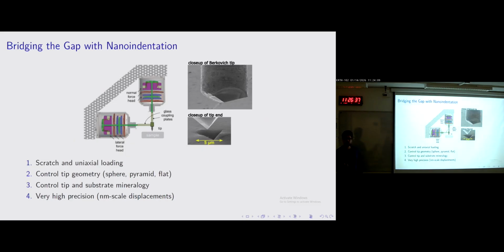That's where nanoindentation comes into play. Nanoindentation is really, really cool and really fun. And this is a diagram of a 2-axis nanoindenter where we have this aluminum frame, we have these 2 force heads, a normal force head connected to the tip, which goes into the sample, and another force head in the lateral position that can translate this tip across the sample. The tip is typically made out of diamond. This is an SEM image of the tip itself. It's small.